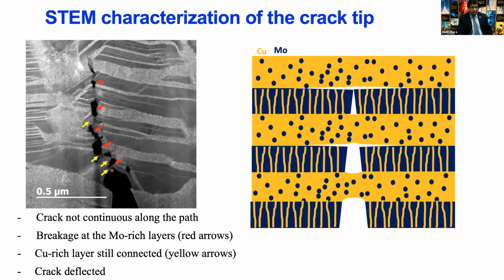You see more crack bridging from the relatively more ductile copper island phase, and there's some crack deflection along the interface also, the copper-moly interface. And the crack was able to jump from here to there. But what is needed is that for each of these, we have to compute to understand which is more important. We have to find a way to compute each unit process and then do this full simulation if we can. This will be very exciting for someone to do, but my collaborators are working on that. But a very, very good question, very insightful.